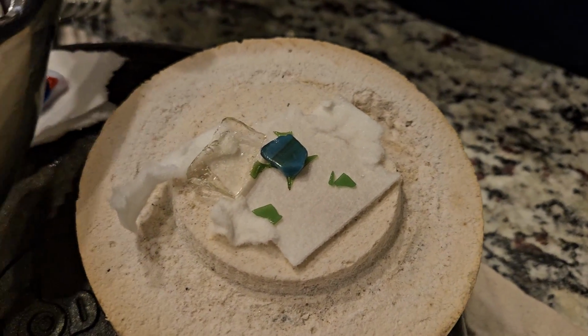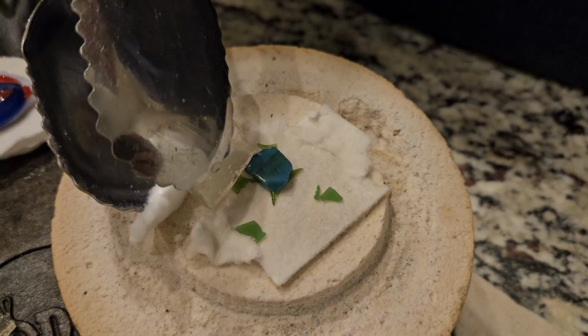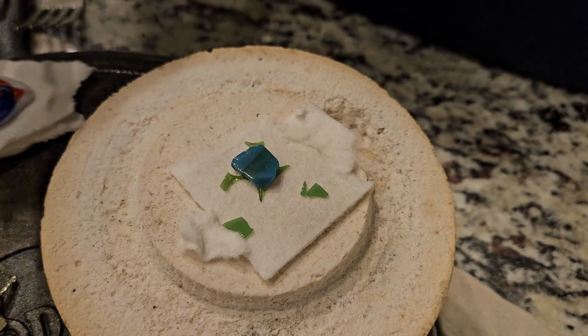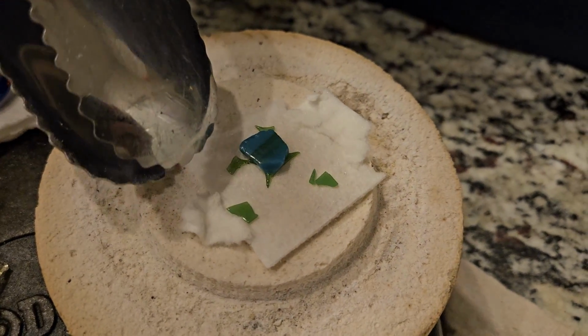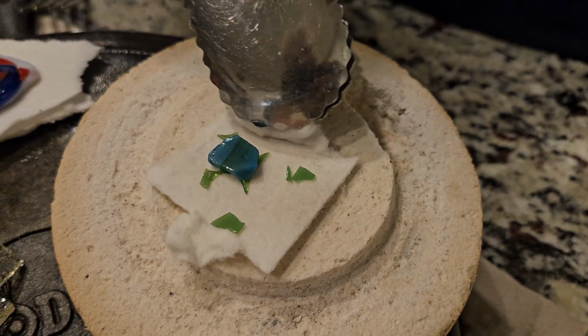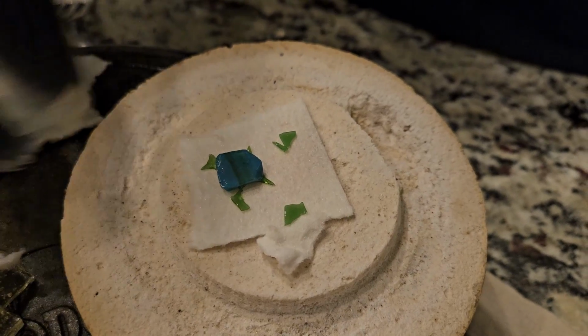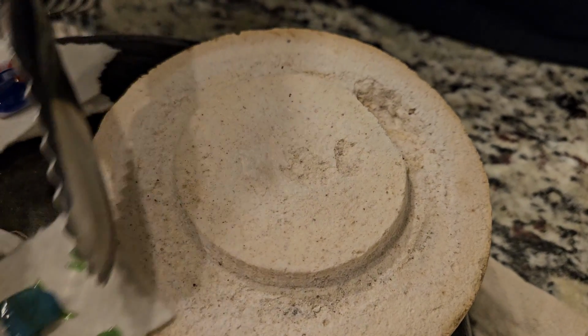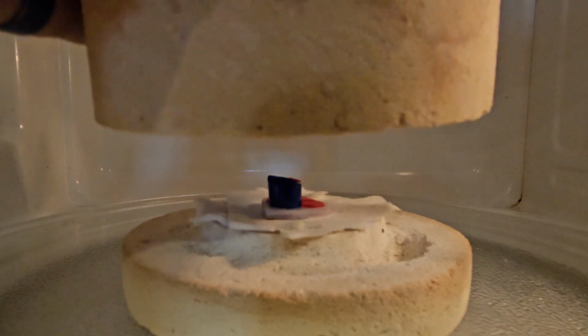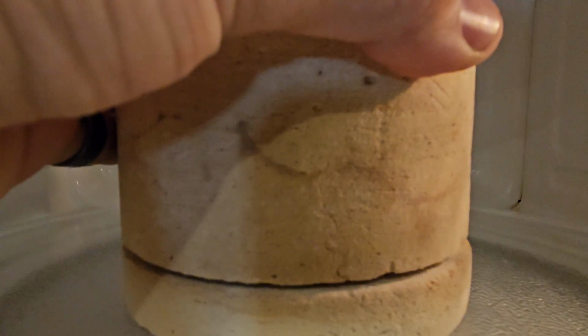And then here is a piece that was not supposed to be fused. So this again was from that assorted glass selection, so this is definitely a non-fusible glass, and that's kind of why it burst open. I don't know if that's because of the bubbles or because of the glass type, but thankfully I heard it pop and was able to grab it out really quick, so none of the glass really stuck too bad to the side of the kiln, and again, we didn't ruin anything.